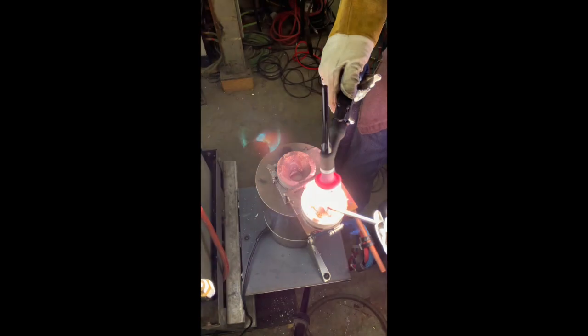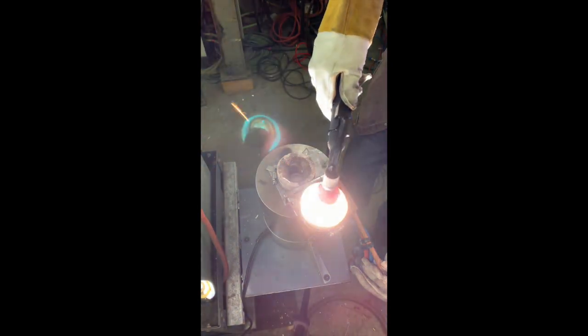And unfortunately, you can't really see anything down there because the arc light is so bright. The arc is about 11,000 degrees Fahrenheit, so it makes fairly short work of melting the HY80 steel, but it still takes a few minutes to get it all to the point where it's molten enough and get the crucible heated up well enough. And there's argon coming out of that torch, and it's keeping it from getting over-oxidized. You can see when the oxygen gets in there, it will get sparking as the steel tries to burn away. But the argon keeps the steel from being excessively oxidized during the melting process.